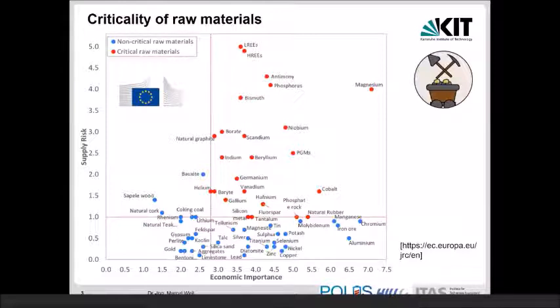And in fact, we did some investigations regarding lithium-ion batteries and the availability of these materials in the long term. That means, if we would use such materials until 2050 for a real transformation of the mobility sector, or the transformation of the energy sector, which also requires a lot of stationary storage facilities. The outcome of all these investigations, and you can find the publications on our website from my group, is that not only cobalt is critical, it's also lithium, copper, and nickel. That means NMC 811 is maybe not the solution to solve the criticality of the raw materials.